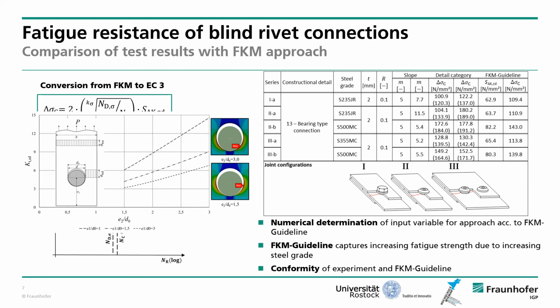For example, the SCF, a stress concentration factor, and we used numerical simulation to determine the stress concentration factor. And as you can see in the diagram, there is a linear relationship between the SCF and the geometric parameters of the joint. And with these input parameters, we determine the fatigue resistance according to the FKM approach.